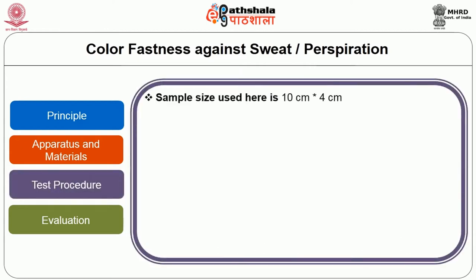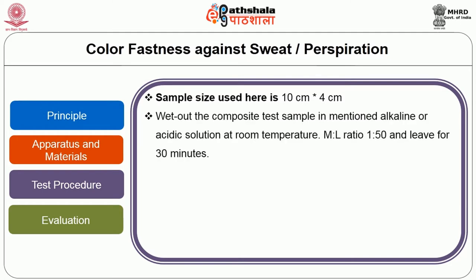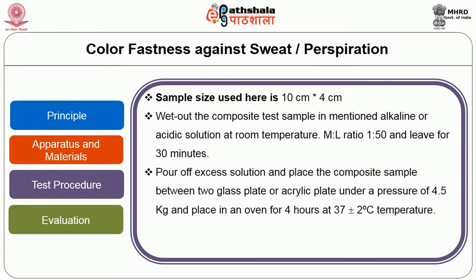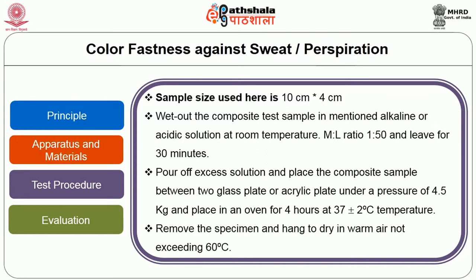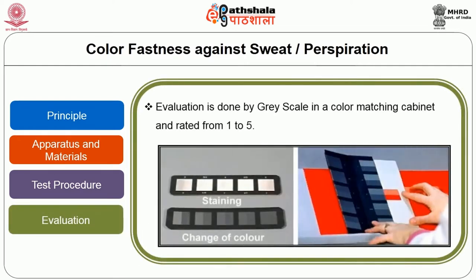Procedure used: the sample size is 10 cm by 4 cm. Wet out the composite test sample in the mentioned alkaline or acidic solution at room temperature. The material to liquor ratio can be 1:50, and the sample can be left for 30 minutes. Pour off excess solution from the sample and place the composite sample between two glass plates or acrylic plates under a pressure of 4.5 kg and place in the oven for 4 hours at 37 plus or minus 2 degrees Celsius. Remove the specimen and hang to dry in warm air not exceeding 60 degrees Celsius. The samples are evaluated using the grayscale in a color matching cabinet and rated from 1 to 5.